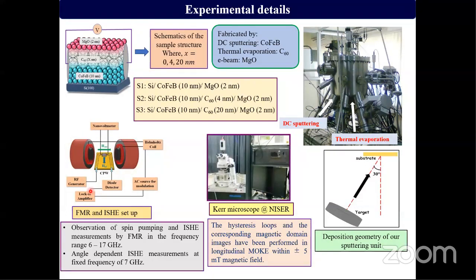So this is the FMR setup, and we have kept the sample in a flip chip manner on top of the coplanar waveguide, and basically we have made the contact at the 2 edges of the sample like this, and we are measuring the voltage using a nano voltmeter.